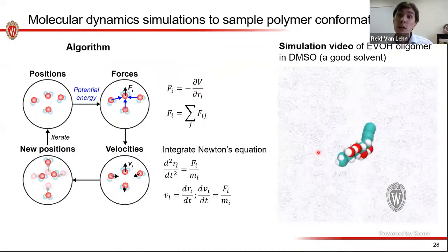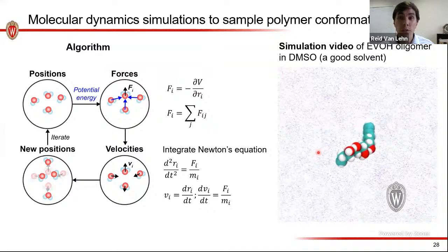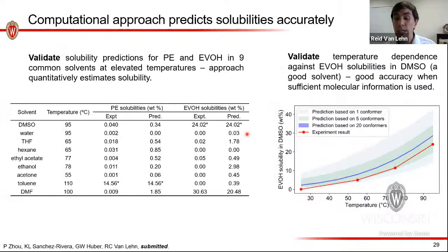What we can infer from the interactions that we observe in these videos is how soluble that polymer is, right? So we can learn something from these simulations about the affinity of the solvent for the polymer, or in other words, does like dissolve like in this particular case. We can do this thousands of times. We can use that to generate computational predictions of the solubility. In other words, how much of that polymer can I dissolve in that solvent? We can then validate these predictions against experimental measurements performed by Professor George Huber and his student Kevin Sanchez Rivera.